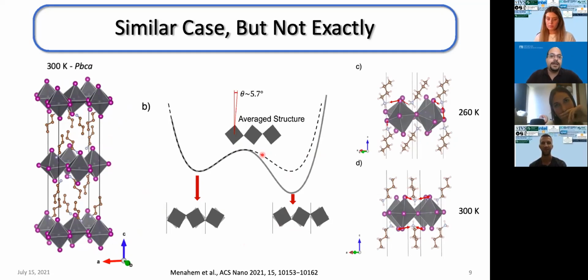Now, what would stabilize one of the wells compared to the other? This would be the strong hydrogen bonds between the amine group in the butyl ammonium and the halide anions, the iodines. If this octahedral rotation doesn't involve a large motion of the organic cation, it would stabilize one configuration much more compared to the other one, giving us the tilted low temperature phase.